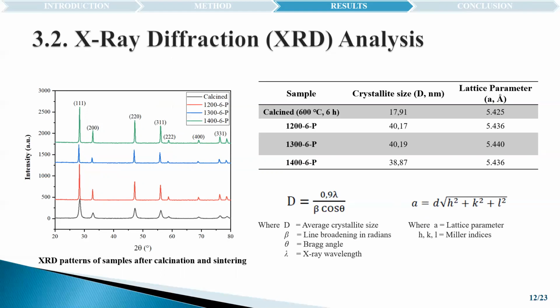XRD patterns show that the calcined powders have reached the cerium oxide cubic structure, and no peak of any other phase was found, and the dopant samarium cation is fully immersed into the cerium oxide phase. After sintering, the peaks became sharper and narrower. That indicates there is an increase in the lattice parameters and crystallite sizes of the samples, which we can see in the table. And of course, the Scherrer equation was used to calculate these average crystallite sizes and lattice parameters.